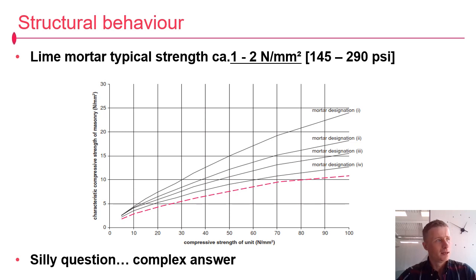Okay, now traditional lime mortar, spectacularly weak, of the order of 1 to 2 Newton per square millimetre. That's for our friends across the pond, somewhere between 150 and 300 psi. Okay, so low strength, which sort of invites the question, with such low strength mortars, how are our old buildings standing up? Now, when you look at the strength curves for the code of practice for load bearing masonry, you'll find that for a weak mortar, you can get very strong masonry as an overall assemblage. And the wee pink one is what I've idealised for what a traditional hot mixed lime mortar might be. Now, you'll find that for very weak mortar, you get ample strength out of your masonry, and you're thinking, like, where does this come from?